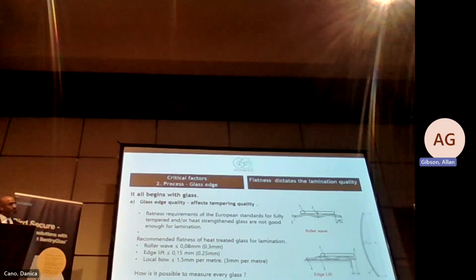So the European standards, which Allan referred to, are EN 12150, EN 1863, and ASTM C1048, which does not have much of a thing, but the most stringent one is the EN standard, which is 12150 and 1863. But if you look at it, those European standards for toughened glass or heat strengthened glass are not good enough for lamination. And specifications are still continuing with the European standard, and we say, oh, we follow the European standard.